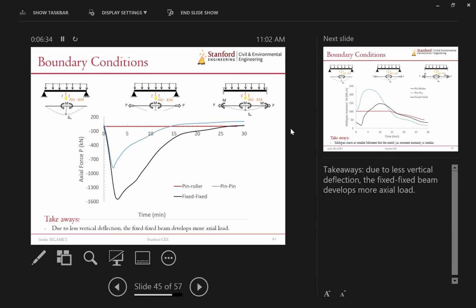In terms of axial force, because the deflections are limited in the fixed beam, you get a much larger axial force. Still not there in terms of yield stress, but it's there. You see, it's much more. So the takeaway from this would be, due to less vertical deflection, the fixed beam develops more axial load. And you can see that there's no axial load in the pin roller, as expected, right? The pin roller is free to expand.